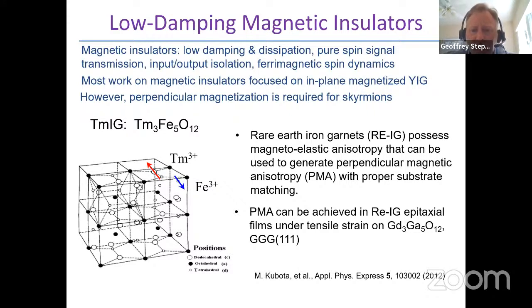By adding a rare earth to such a material, one can induce things like a perpendicular anisotropy, as I'll show you later. One can induce a Dzyaloshinskii-Moriya interaction. While the damping does go up a little bit, it still remains considerably lower than what one has in metals. And in addition, as opposed to metals, in which the currents that drive the dynamics also dissipate energy, pure spin currents can be used to drive dynamics in insulating magnets. And that can be done potentially with much lower energy.